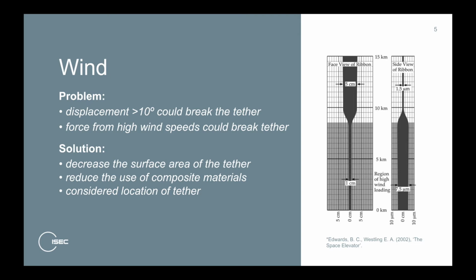Edwards also mentions that drag seems to increase in areas where composite materials are used. This would be because microscopic holes are being filled, and so naturally we should avoid this where possible. Once again, we must also pay close attention to the location of the space elevator, choosing a place where there is low wind speed, and hopefully avoiding the problem altogether. Luckily, the location west of the Galapagos Islands, which we saw in the last slide, also tends to have low wind speeds, and because it's on the equator, can't sustain hurricanes.